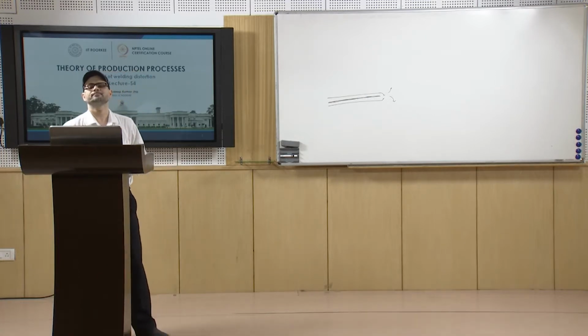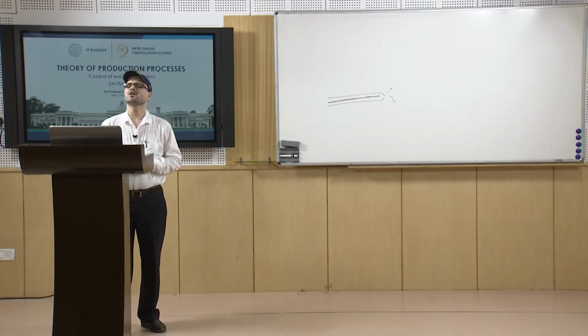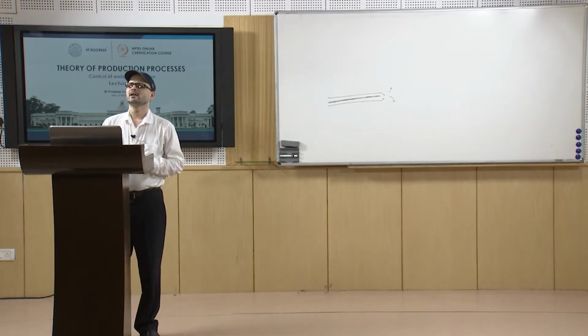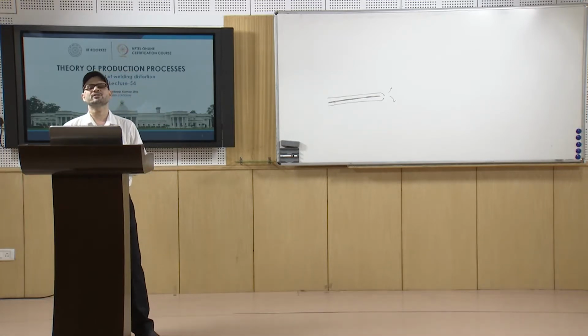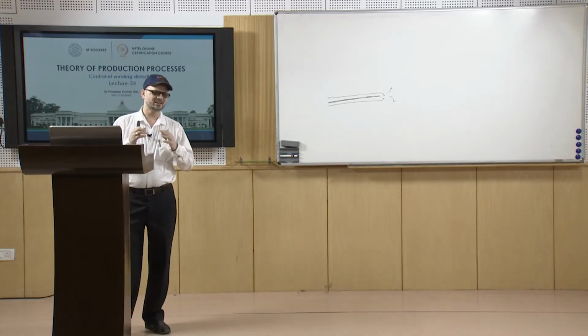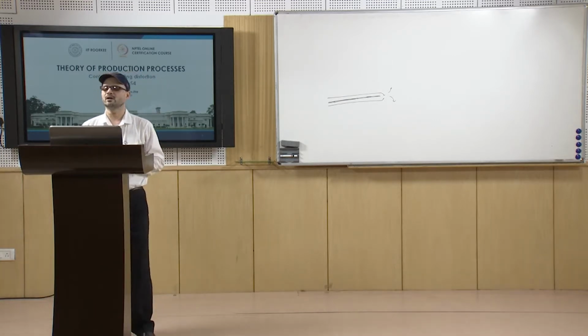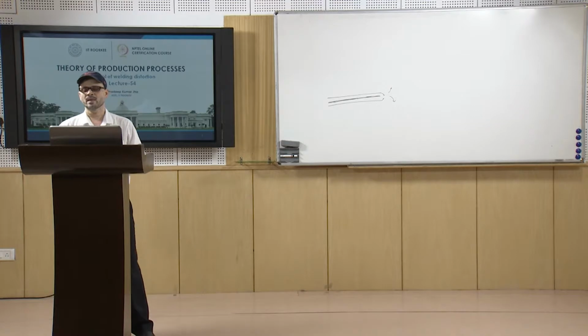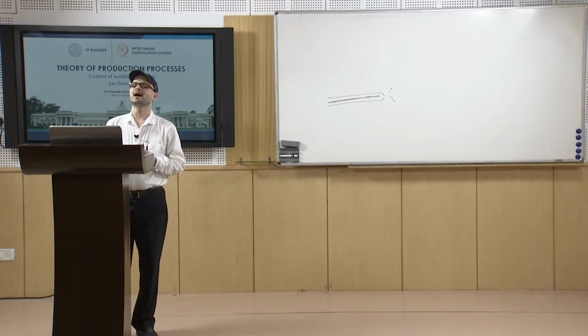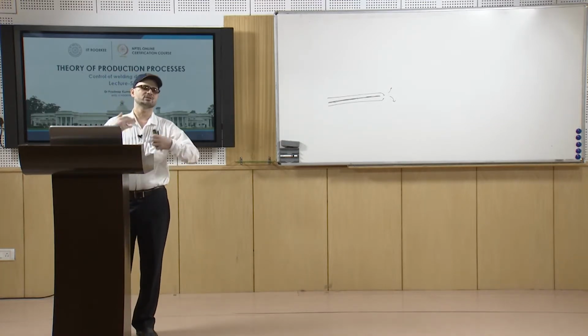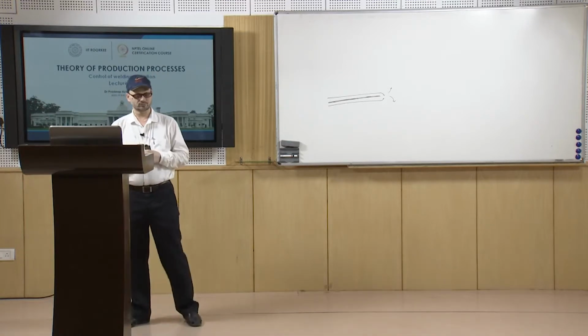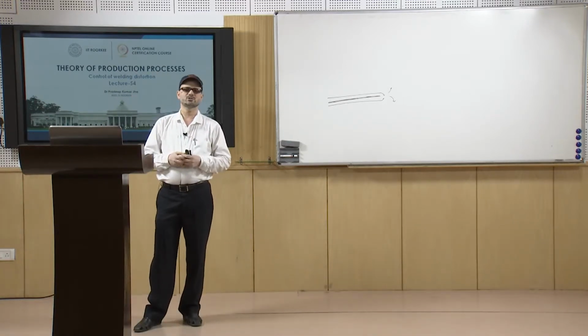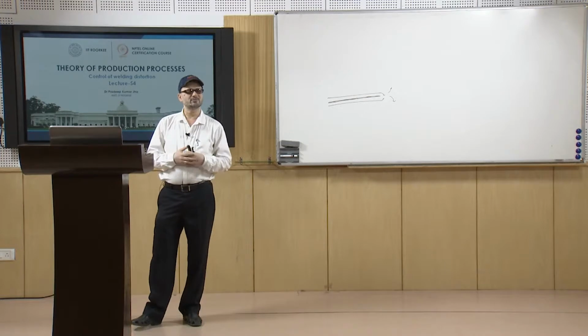Then hardening and cracking of the tack weld may occur if of inappropriate volume. So, if there is inappropriate volume of the tack weld metal, then in that case there may be hardening of the tack weld, because that has to transmit the heat. So, it will transmit the heat, it will cool fast.